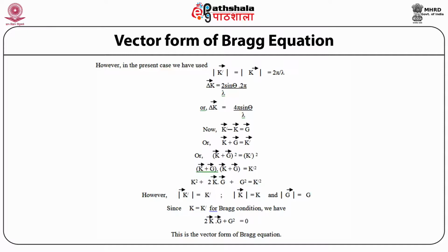Now K prime vector minus K vector is equal to G vector, or K vector plus G vector is equal to K prime vector. We can say K vector plus G vector whole square is equal to K prime square. K vector plus G vector dot K vector plus G vector is equal to K prime square. K square plus twice K vector dot G vector plus G square is equal to K prime square. However, modulus of K prime vector is equal to K prime, modulus of K vector is equal to K, and modulus of G vector is equal to G. Since K is equal to K prime for the Bragg condition, we have twice K vector dot G vector plus capital G square is equal to 0. This is the vector form of Bragg equation.